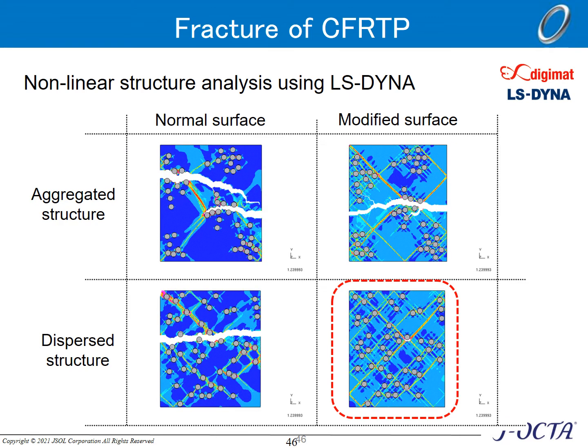Finally, we performed the calculation of the fracture using LS-DYNA. See the figure at the bottom right. This is a case where the fibers form a dispersed structure, and a modified surface is set. You can see, this case is holding up to the end. The aggregation of the fibers causes stress concentration. Also, if the interface is weak, it will quickly break down.